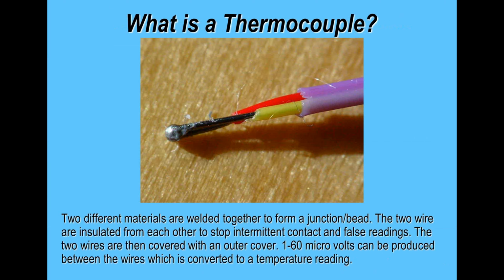The thermocouple bead you see at the end or the junction of these two wires is what measures temperature. The two wires coming away from the bead should not touch. If they touch, where the two wires touch, that is where you're actually measuring temperature. So what you want to do is make sure the insulation is preventing the actual wires touching away from the bead. On this particular example, you've got insulation and you've got an outer insulation to protect that, to give it a bit more stability.